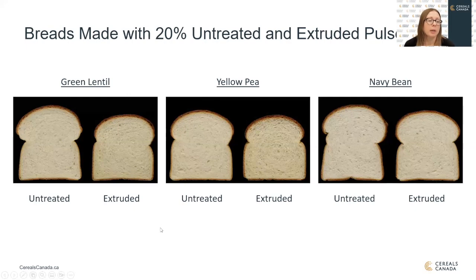So we also used these in our end product applications. Again, we used them at 20% inclusion for bread. You can see the extruded treatment decreased the loaf volume. The crumb structure is a little bit more open and coarse. And the color is a little bit more creamy and yellow. Flavor-wise, both yellow pea samples were unacceptable. The only one that really showed an improvement was the extruded navy bean, where the flavor seemed more neutral, but there was no difference noted between the green lentil samples.